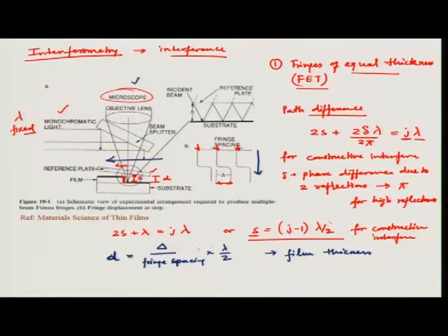So, now you can observe the delta divided by fringe spacing only if your fringe width is small enough, right. If the fringe widths are very large, then it is very difficult to measure this delta, the change in shift. So, for highly reflective surfaces, fringe width is about 1/40 of fringe spacing.